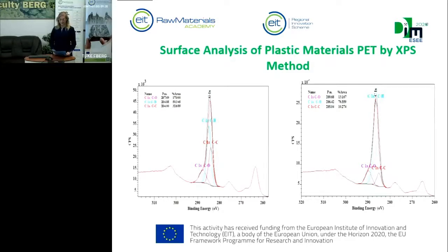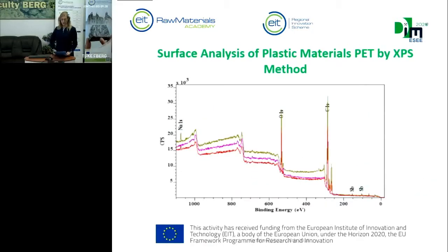At the alkaline hydrolysis by treatment with sodium hydroxide, the disappearance of the double bond carbon-oxygen was observed, which is associated with the binding of sodium from the sodium hydroxide solution to the oxygen from the ester group.